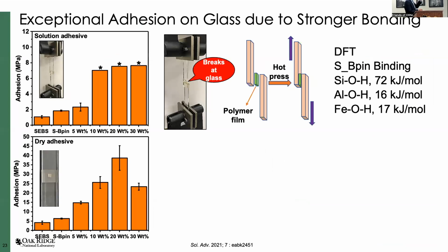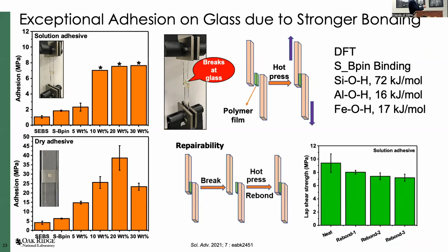As I mentioned initially, we couldn't take it out from the glass. We did the same test. Again, the higher this value, the better. But when you have the nanoparticle addition, the glass actually breaks before the adhesion fails. That's how strong it is. So what we have to do is minimize the area. With a much smaller area, it can take the force, and then you can measure it. So that's pretty strong.